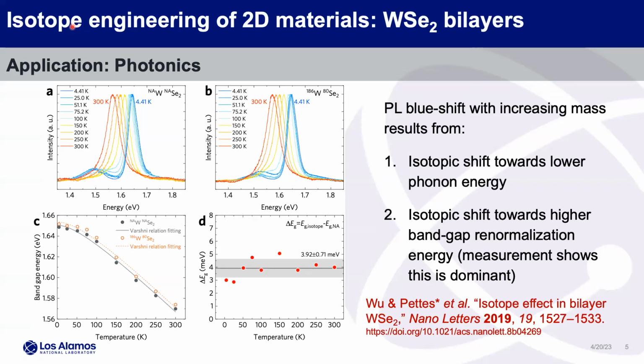So 4 millielectron volts over the entire temperature range doesn't saturate at low temperature, as you would expect for something that was mediated by defects. And then when we started looking closer into this, you can see it's 4 millielectron volts across the whole temperature range. What we started seeing is that you should get this kind of change if you have band gap renormalization. We didn't measure ARPES, but ARPES measures band gap renormalization. That's what it's measuring.